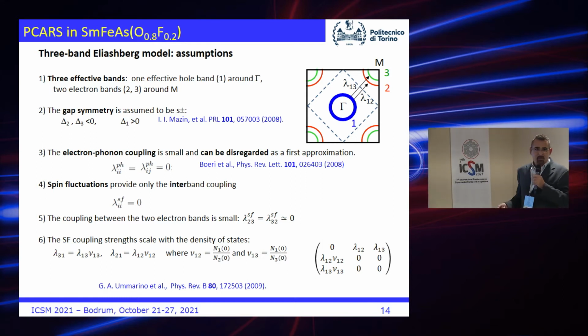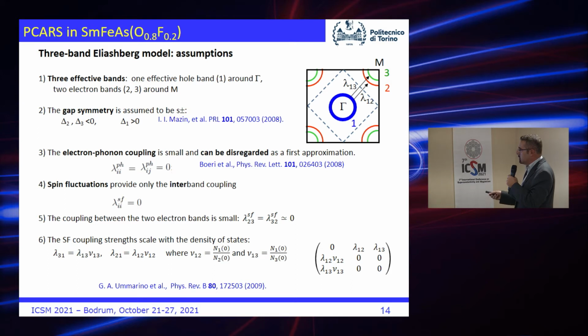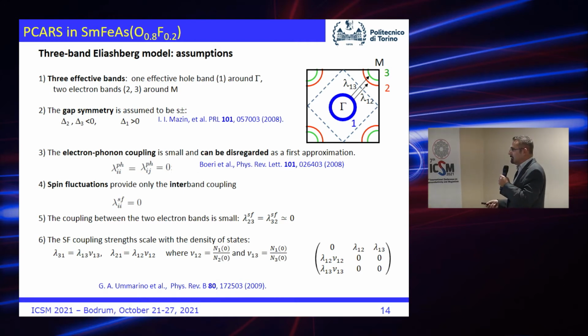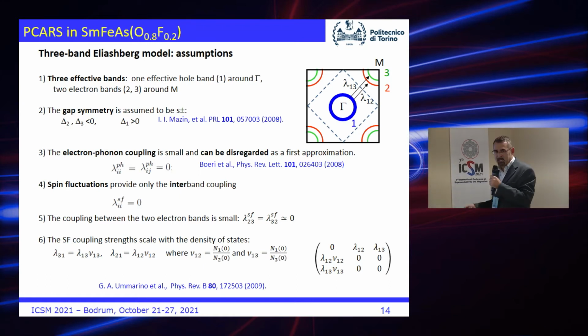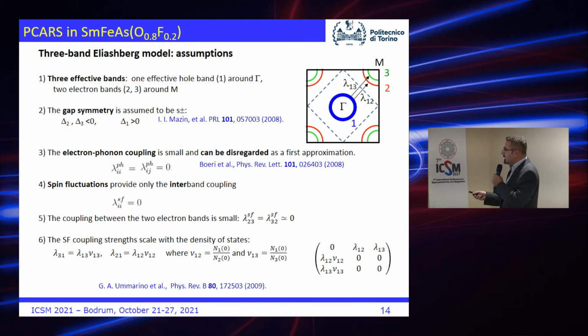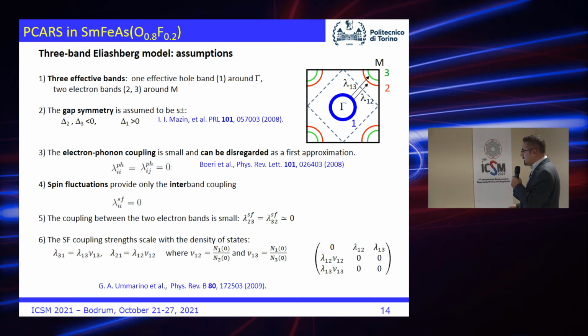We assume that the gap symmetry is s plus minus, so these gaps are isotropic individually, but this one is negative and this is positive. This is the line of nodes. Then, the electron-phonon coupling, we know from literature that it is very small in these compounds, of the order of 0.2. So to simplify, we disregard it completely. We assume that electron-phonon coupling is absent. Then spin fluctuations are present instead. But spin fluctuations cannot provide intra-band coupling, because within a single band it would be pair breaking with s-wave gaps. So they can only couple the bands that are here with the bands that are there. But they do not couple band 2 with band 3, so this again is 0. And in the end, we have this matrix of lambda values, lambda 1,2, lambda 1,3, that are these ones shown here.